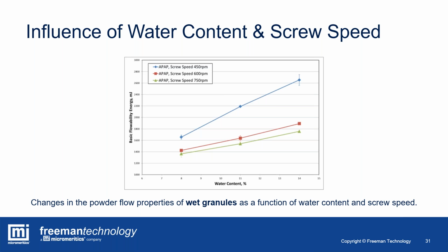So this is changes in flow properties of the wet granules, directly from the granulator screw before it goes into the dryer, as a function of water content and screw speed. This is for the acetaminophen, and in all cases you can see that as you add more water, you end up with a higher basic flowability energy, so that represents denser, bigger, stronger granules. And interestingly, quite a significant effect on screw speed.